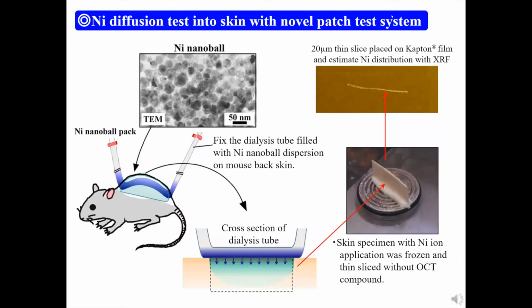We tested how the nickel ion released from the nanoball was absorbed into the skin with an animal test. The nickel nanoball suspension was applied on the mouse back skin. After a certain period, the mouse was sacrificed and the skin cross-section was used for XRF elemental distribution analysis.